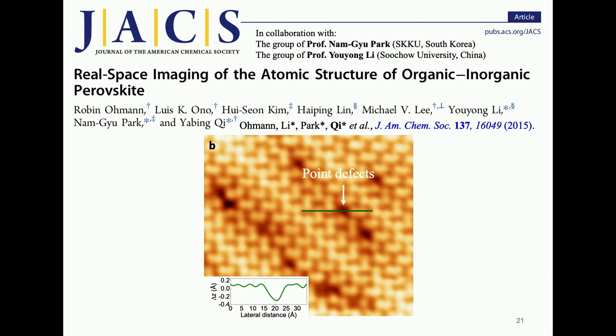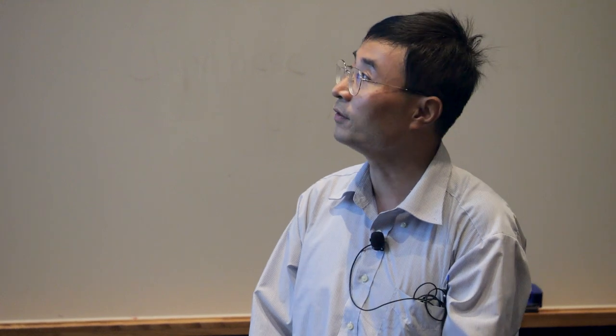As you can see from the line profile on the bottom, at the defect site, the STM height is lower than the surrounding region by about 0.3 angstrom. Another observation of our STM study is that, on average, the density of point defects is below 1% with respect to the total number of the bromine surface ions.